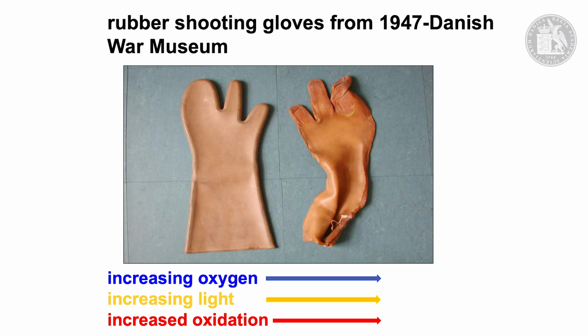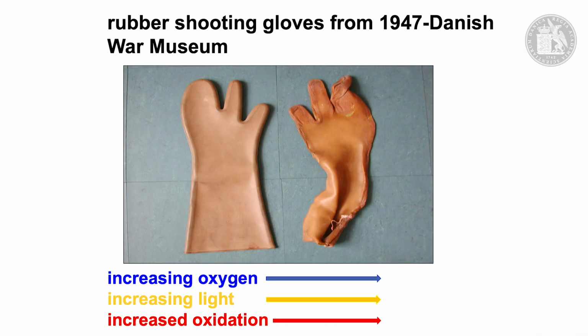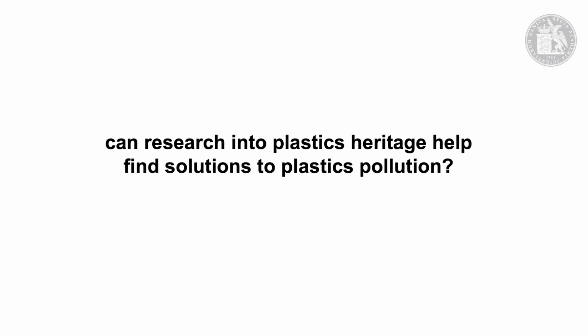We can compare this. We've known in the museum for many years that light, especially ultraviolet light, degrades plastics and other organic materials. This is a pair of rubber shooting gloves from the War Museum, as it's called now. They're from the same pair from 1947, but the one on the left has never been used and has sat in a dark box with a little bit of oxygen, of course, but no light for many years. But its partner has been both used and exhibited and had light and oxygen, and it shows clear signs of increasing oxidation. So the two things fit together. So we can agree that research into conservation, degradation of plastic objects can certainly contribute to our understanding, and it will, I hope, of what happens in the marine environment and when plastics are waste.